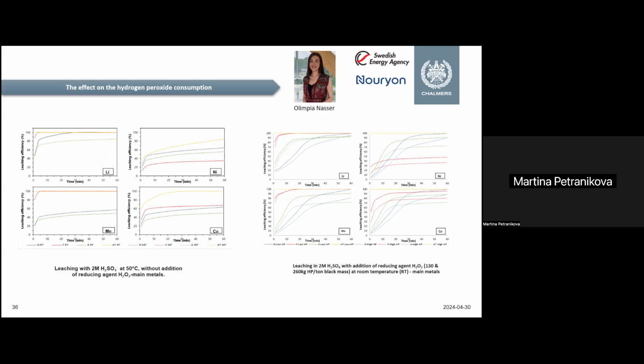What we have seen is that if the companies use pyrolysis, then usually a very small amount of hydrogen peroxide is needed to achieve complete recovery, and it's also very fast. If you look at the red lines, you can see that even though we dosed a lot of hydrogen peroxide for the incinerated samples, it didn't help that much for cobalt and nickel. So incineration is usually a very bad option for battery recycling, because if you reach some temperatures, you can form phases which are not that leachable under these conditions. So it can be harmful for the recycling of batteries.